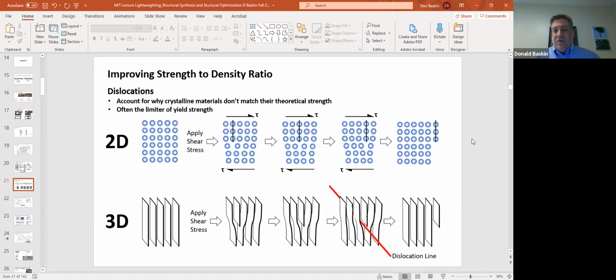You can reduce them or get rid of them by heating up the material and annealing them out, and then you can create them again when you start bending the steel or aluminum or titanium, whatever it is. When you bend it back and forth, you can recreate these dislocations and move them around. But keep in mind that there are literally kilometers of dislocation line inside a grain that might only be 10 or 100 microns wide. Make sense, guys?